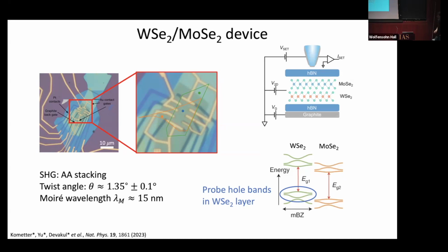So the rule of thumb that you should have in mind is the Moiré wavelength is about 19 nanometers divided by the twist angle. So the heterobilayers, the Moiré wavelength is usually, well, 5, I don't know, I guess 5 to 10, depending on materials, nanometers from the lattice mismatch. And for these twisted molybdenum ditelluride samples that Xiaodong, for example, was talking about earlier, that corresponds to a Moiré wavelength at 3 degrees of, again, somewhere in the range of 5 to 10 nanometers. So on the scale, at least for transition metal dichalcogenides, this 15 nanometer wavelength is quite long.